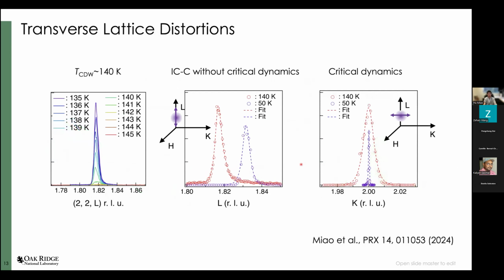So here I want to jump onto the material and show you that in europium aluminum 4, it really forms a transverse CDW. On the left panel, I show you the X-ray diffraction data as a function of temperature, and we can clearly observe the CDW superlattice peak around 140 Kelvin. Interestingly, if you do an L scan at the CDW peak and change the temperature, we don't see the expected critical dynamics, meaning the peak width doesn't change with temperature. What you see is only the peak position change, which is what you expect for an incommensurate CDW.